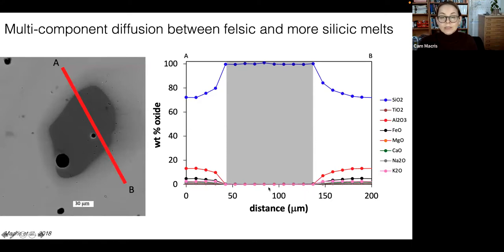So now we're going to look at some data from this tektite. What I'm showing here is weight percent oxide on the y-axis versus distance on the x-axis, distance as we move from A to B across this Le Chatelierite. So we're moving from the matrix glass inside the inclusion and then back out the other side. And what we see here are these compositional gradients that for silica increases from about 75 weight percent in the matrix to about 100 weight percent inside of the inclusion, and then back out the other side. And then the inverse for aluminum in red here, aluminum has about 14 weight percent, but it drops to about 0 inside of the Le Chatelierite.